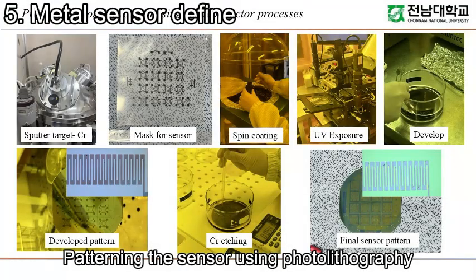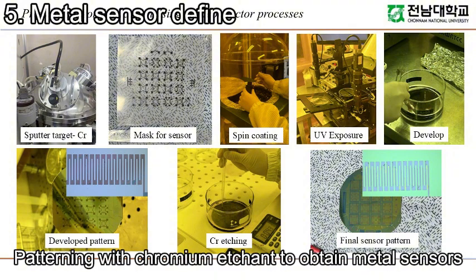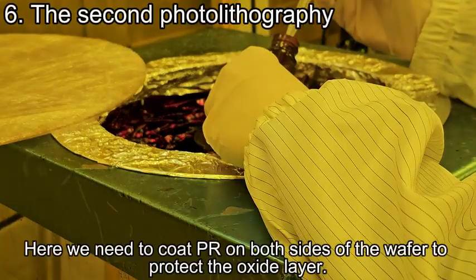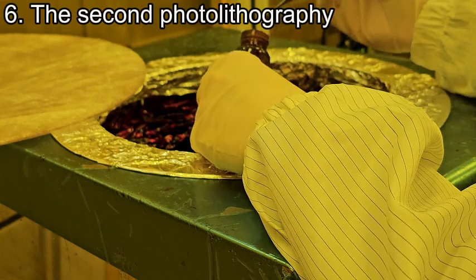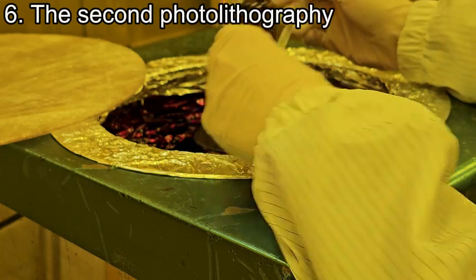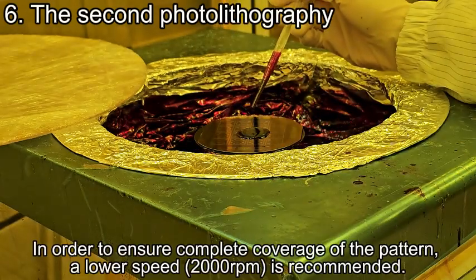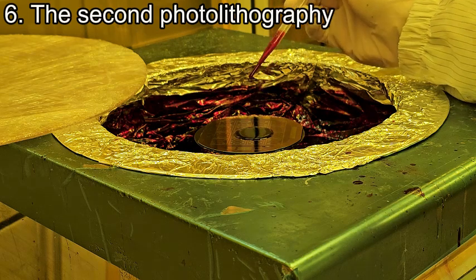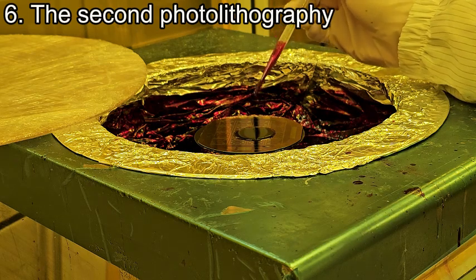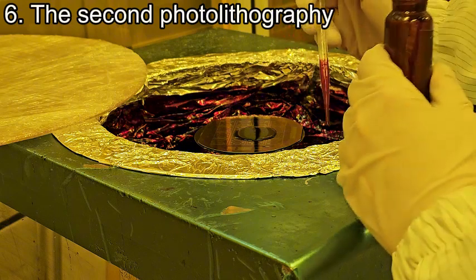Patterning the sensor using photolithography. Patterning with chromium etching to obtain metal sensors. Here we need to coat PR on both sides of the wafer to protect the oxide layer. In order to ensure complete coverage of the pattern, a lower speed of 2000 revolutions per minute is recommended.